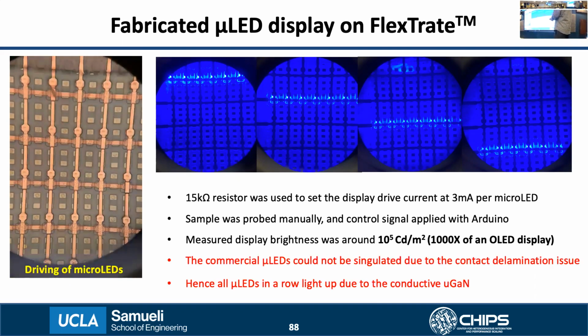These samples, however, because we use commercial micro LEDs, could not be singulated. Because of the contact delamination issue, all the LEDs in a row light up, and we were able to show this display only in a row scan operation because of the thin UGAN between the devices that tends to short adjacent devices. But since this is just for demonstration purposes to show that we can heterogeneously integrate micro LEDs with the driver ICs, this would be a very good prototype for that.